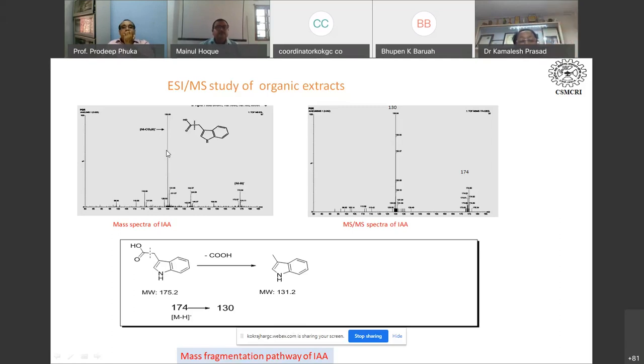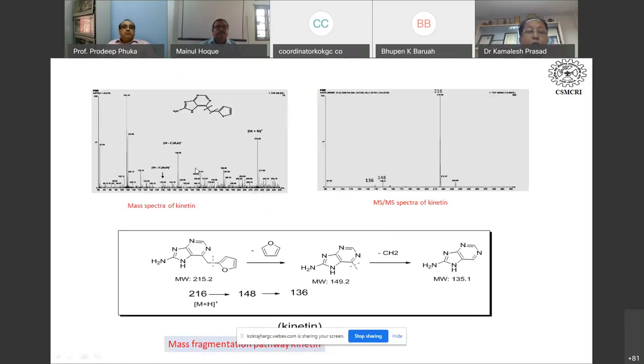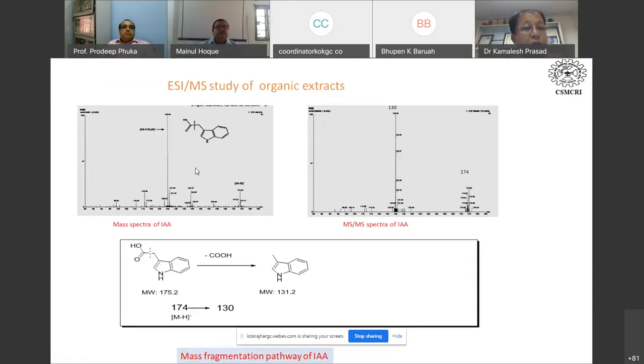If I run the standard indoleacetic acid in the mass spectrometer and get a fragmentation like this, it does not mean that the molecule is indoleacetic acid. We have to fragment the molecular ion peak again, so we fragment this 174 by MS/MS, tandem mass spectrometry. So we get two fragments. This is a very distinct fragmentation. We are not getting any other fragmentation, only two distinct peaks: one is the molecular ion peak, one is the daughter ion peak.